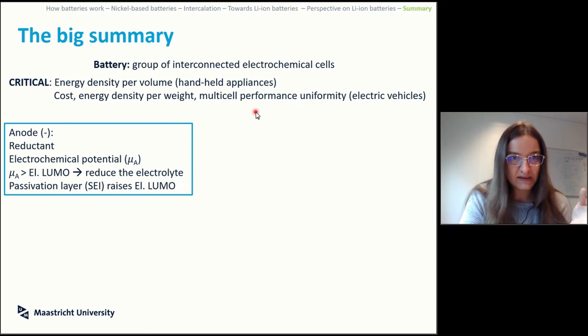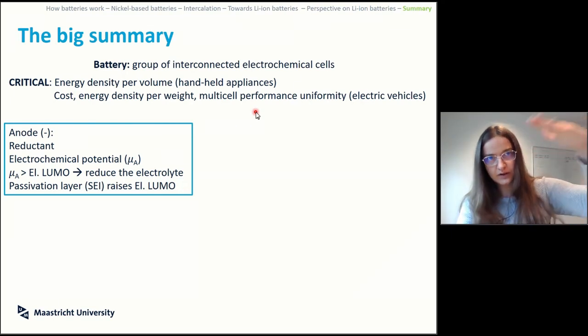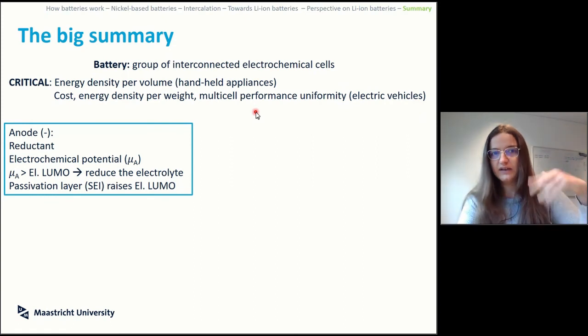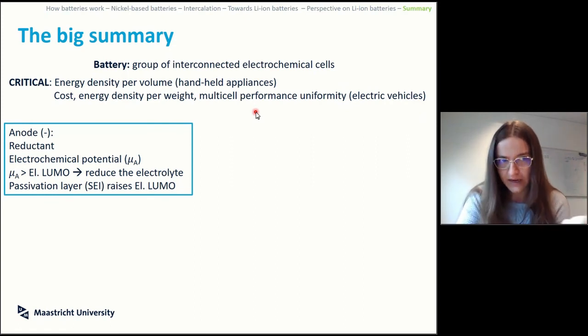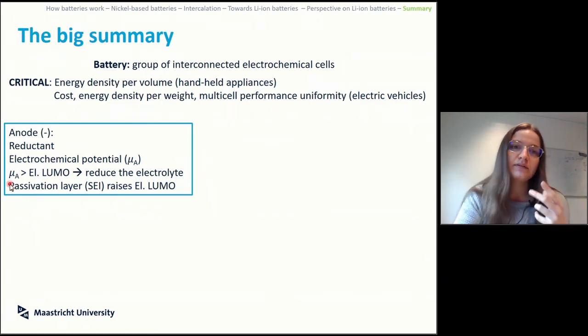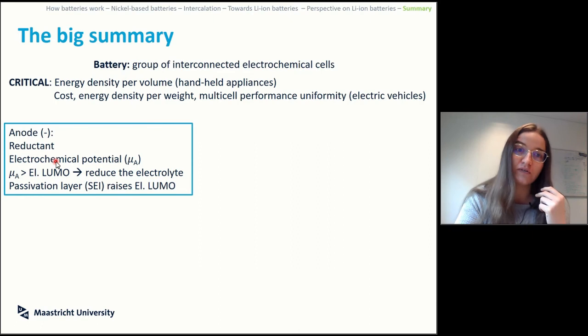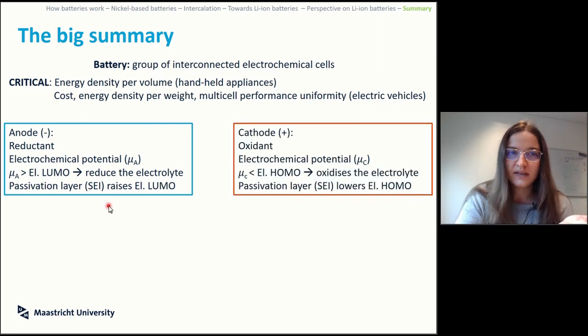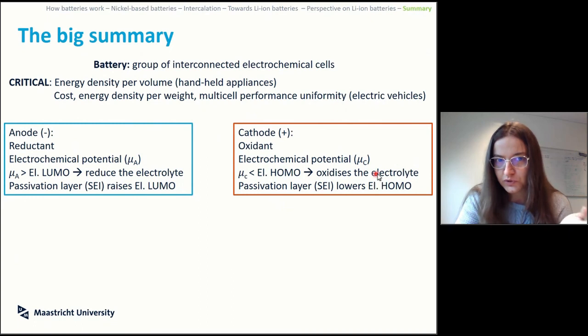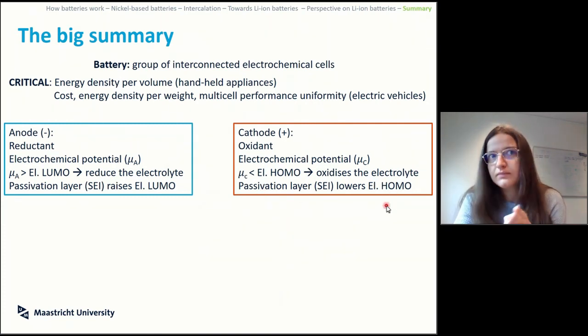Your anode is the reductant. The electrochemical potential of the couple that is getting reduced and oxidized is called mu A. This thing needs to be higher than the LUMO of the electrolyte, otherwise the electrolyte will reduce. You can tweak this thing by having a passivation layer, the solid electrolyte interface, on top of this. The cathode is your oxidant, electrochemical potential mu C. It needs to be lower than the electrolyte HOMO, or otherwise it will oxidize the electrolyte. If you passivate the cathode, at your own risk, you can tweak this potential.